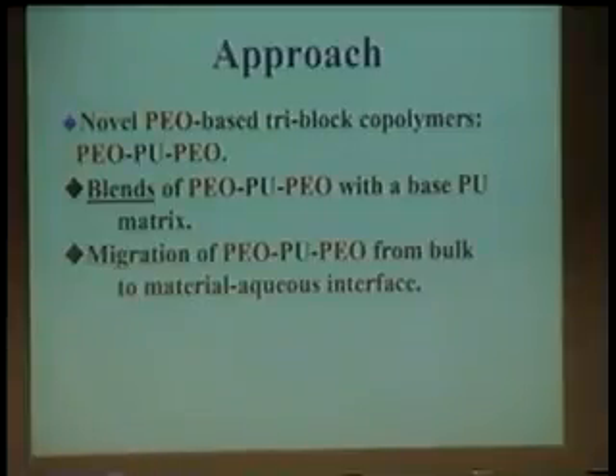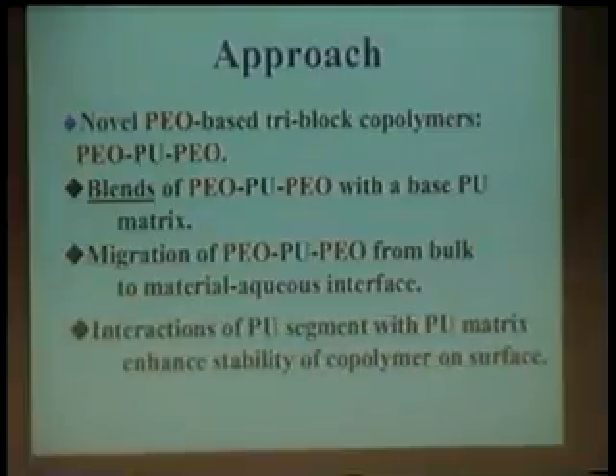And furthermore, the interactions between the middle segment of this copolymer and the matrix itself should enhance the stability of the copolymer and effectively help to anchor it at the interface. Otherwise, we might lose it into the aqueous system.